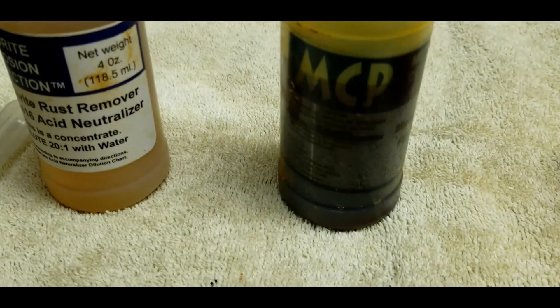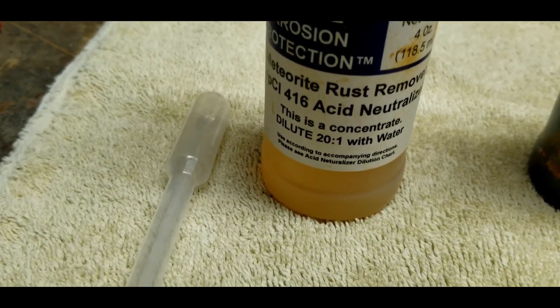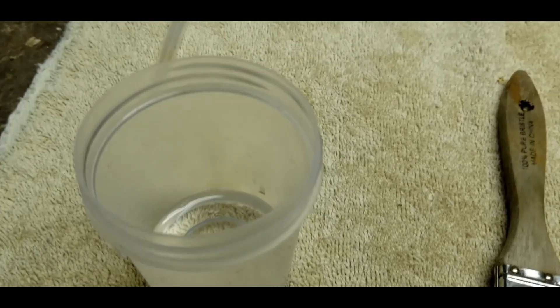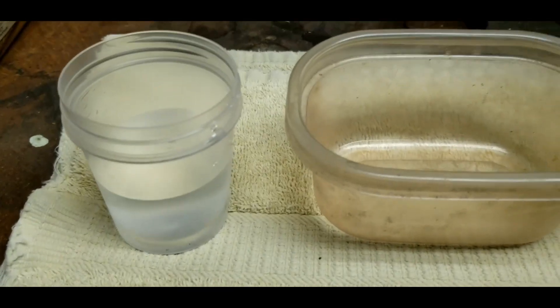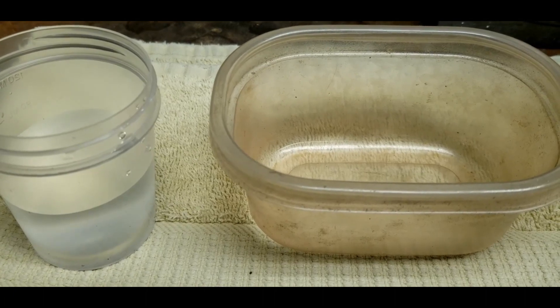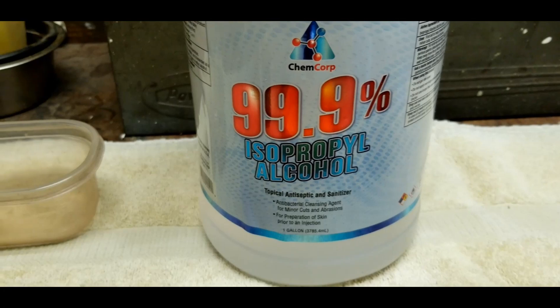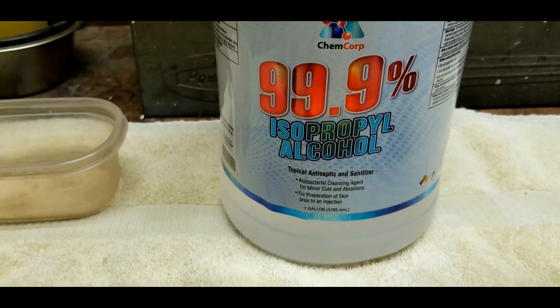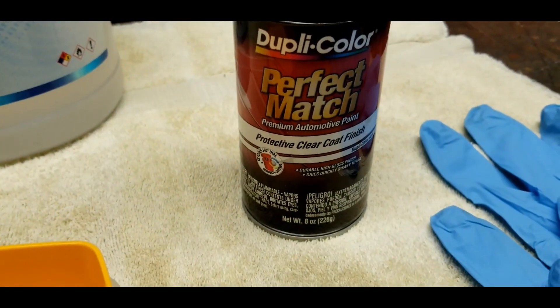I've got my ferric chloride right there. I have my acid neutralizer — the dilution 20 to 1 has already been done. Doesn't take much, just brush it on and wash it off. Got some distilled water and another little tub ready to go. To pre-clean the meteorite, I used some 99.9% isopropyl just to get rid of any surface greases. Once the process is done, I'm going to preserve it with some automotive clear coat.